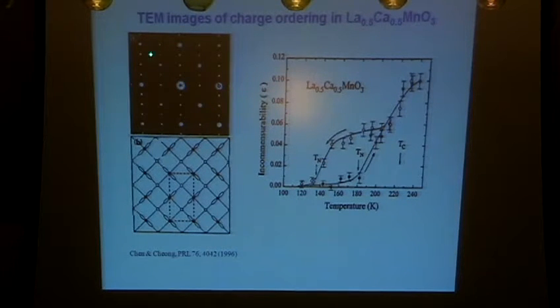And those diffraction spots are very naturally interpreted in terms of this structure of 3 plus, 4 plus, 3 plus, 4 plus, etc. Double period. So that's what you see at low temperatures, and that's perfectly fine. An odd thing happens when you warm this up.